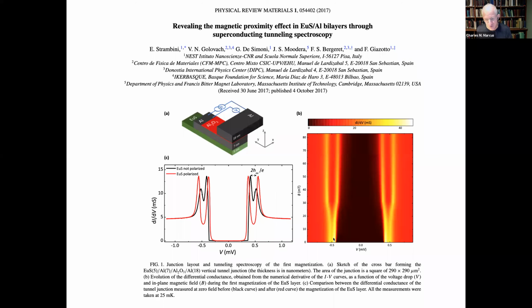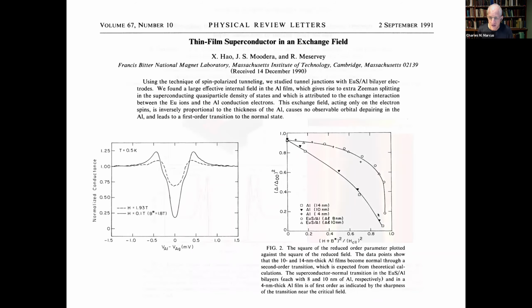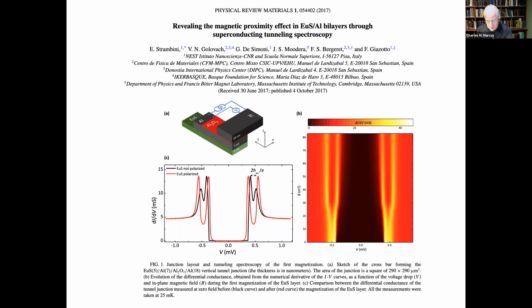And what this means is that though you've induced a large spin splitting, you haven't collapsed the superconducting gap in a way consistent with this first order like feature where the gap persists until it crashes. So here they haven't crashed the gap, so the gap lives though the splitting is large.